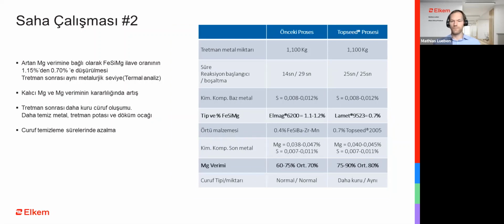Case study number 2. Again, the reaction starts later, so a more stable process. It started before the optimization at 14 seconds and now at 25 seconds. There's also a reduction in ferrosilicon magnesium addition from 1.15 to 0.7%, thanks to the improvement of the magnesium yield from 70% to now 80%. The same metallurgy after treatment has been achieved, controlled by thermal analysis.